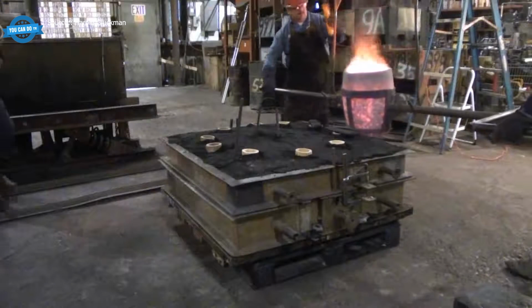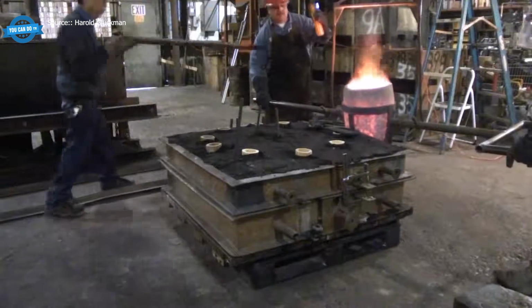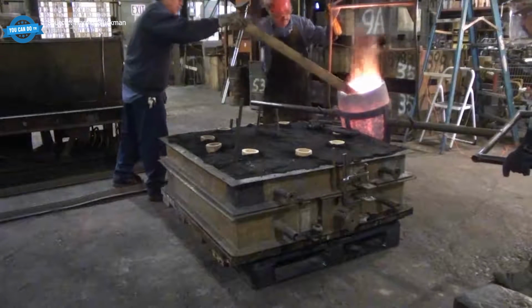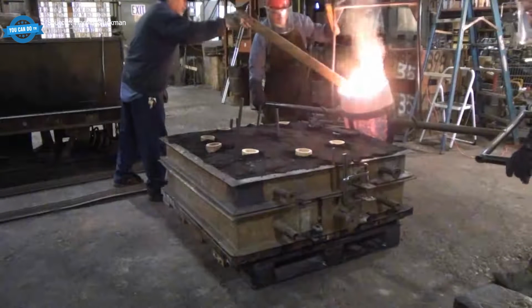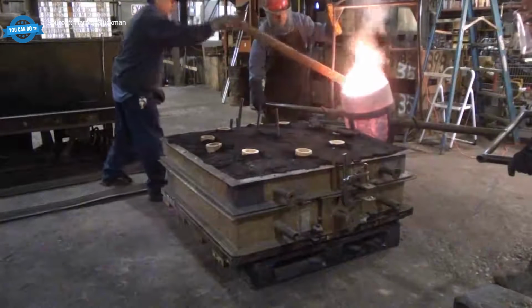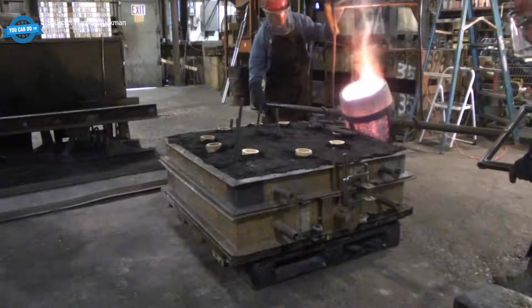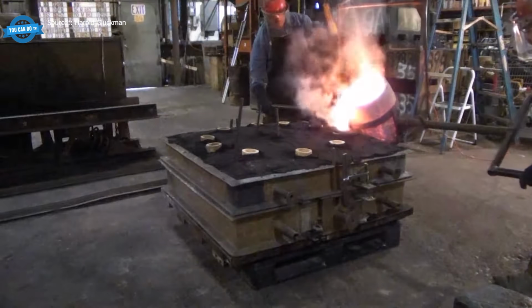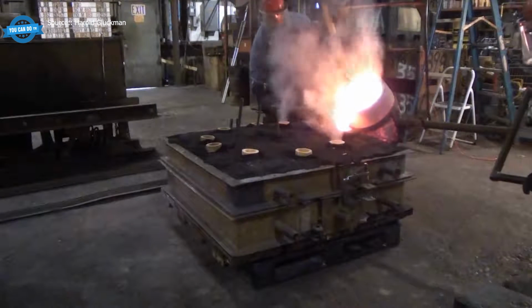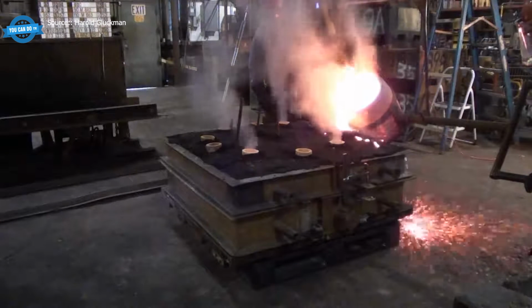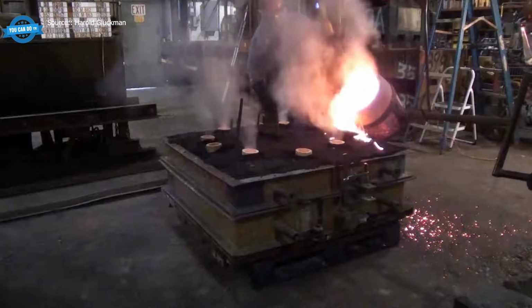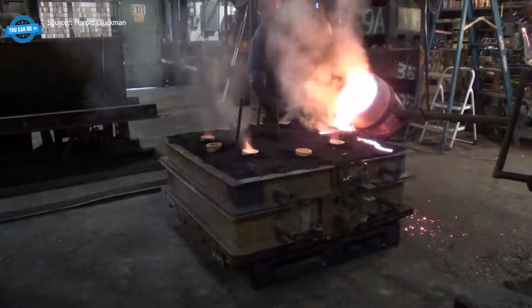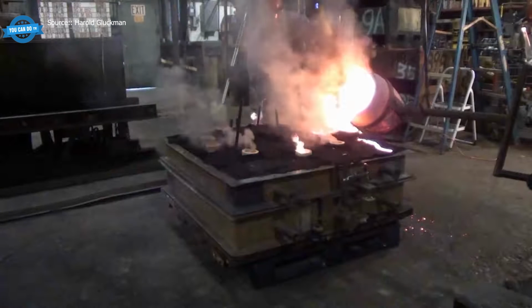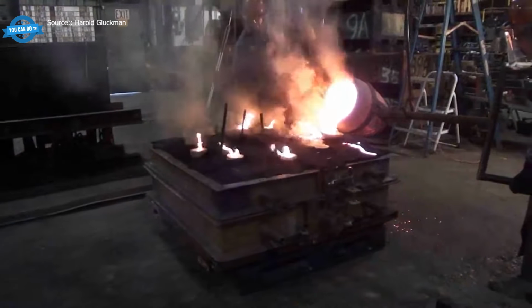A big bronze pour starts in an induction furnace, where copper and alloying elements are melted together at temperatures over 1,100 degrees Celsius. The molten bronze is transferred to a crucible, which glows almost white as workers move it toward the mold. Bronze at pouring temperature is heavy, hot, and unforgiving. One bad spill and the shift ends immediately.